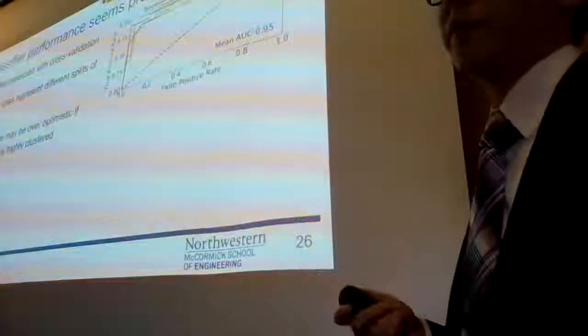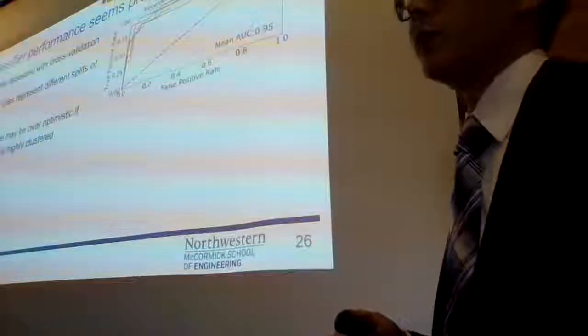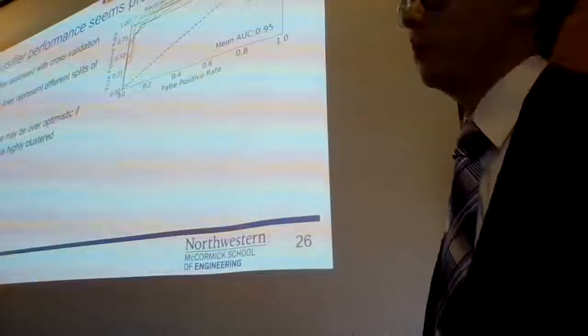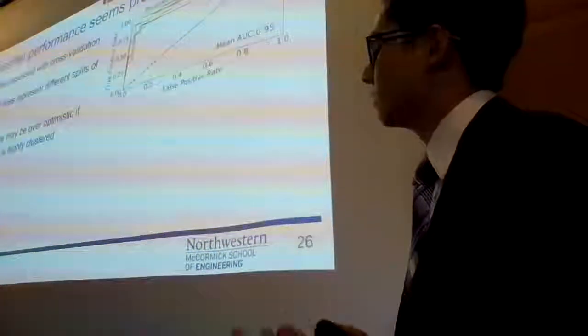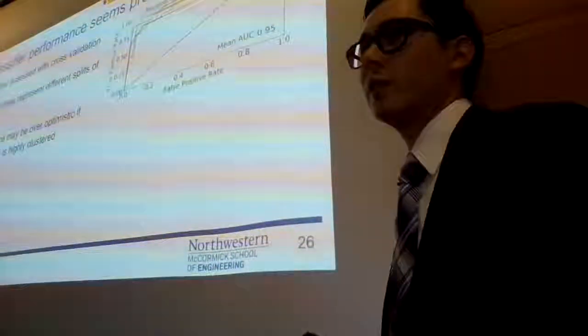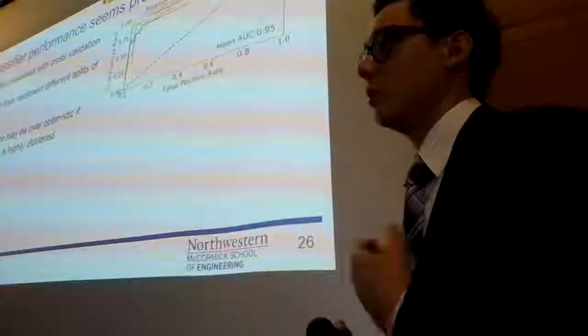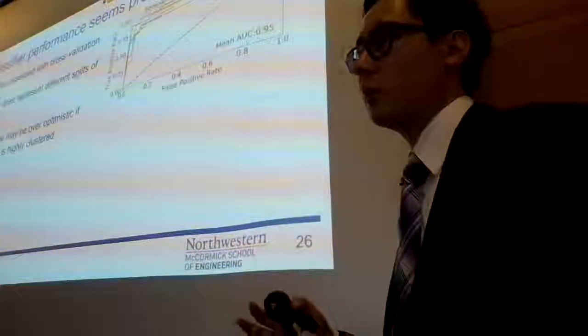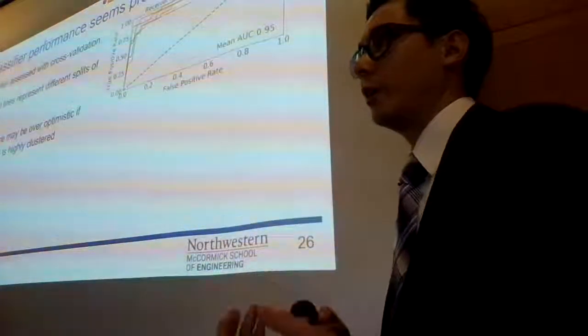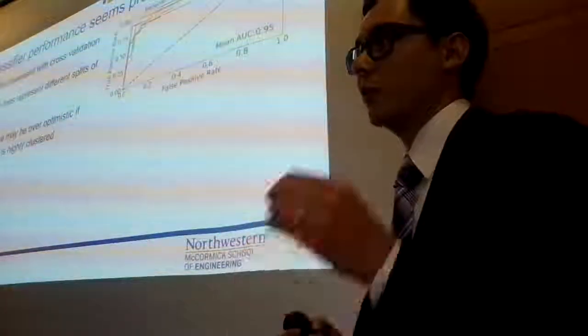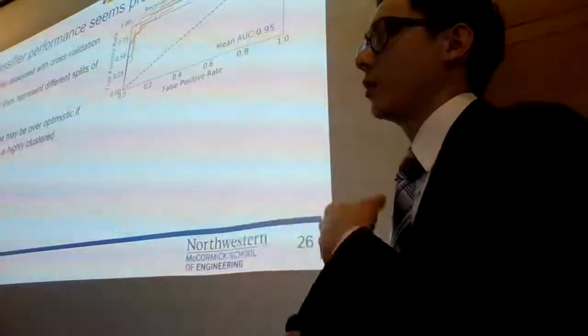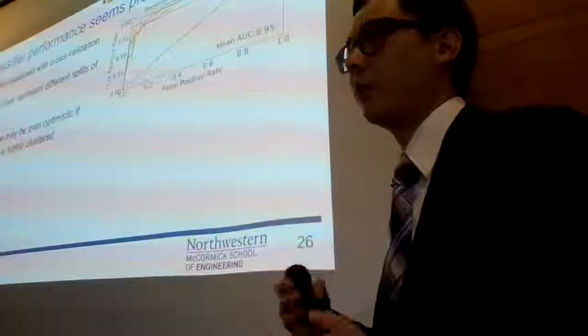However, this performance could be over-optimistic if the data set is imbalanced. So say there's a lot more materials that don't have metal insulator transitions than do have metal insulator transitions, which is the case in my data set, but even more so would be in a larger data set. And the other reason it might be over-optimistic is if there's a high amount of clustering. Say you're working on superconductivity and you know all about pnictides and BCS theory superconductors, you would very likely have a high predictive accuracy of a machine learning model trained on those within those materials, but you might not predict the cuprates to be superconducting because they're so different from the particular clusters of materials you have known.